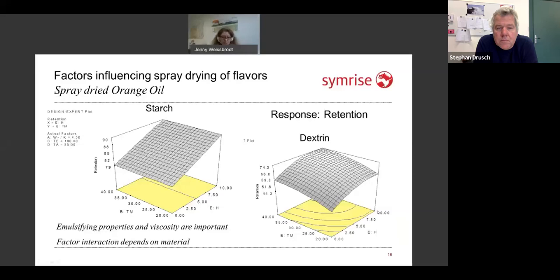For our non-emulsifying material, the homogenization is even more important, because here you don't have this film building which the starch will do on the surface of your oil droplet. You just have the chance to distribute your active as fine as possible within your continuous phase to have any kind of retention. And this is, of course, supported by the solid content, because a higher solid content means you have a high viscosity, and this will stabilize your emulsion too.